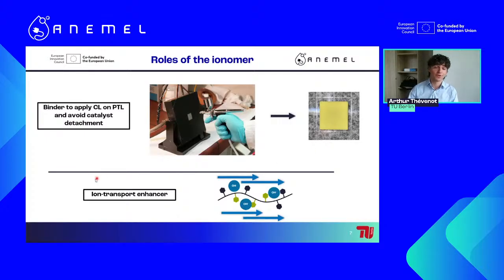The second role of this ionomer is as an ion transport enhancer. Thanks to its ionic groups, it will help the transport of the ions that are oppositely charged. In our situation, our ionomer has positively charged groups, these imidazolium groups. As it's positively charged, it will help the flow of negatively charged ions, also known as anions. And as we are in alkaline medium, we want to enhance the transport of the hydroxide ions, these OH- ions that are flowing through the system.